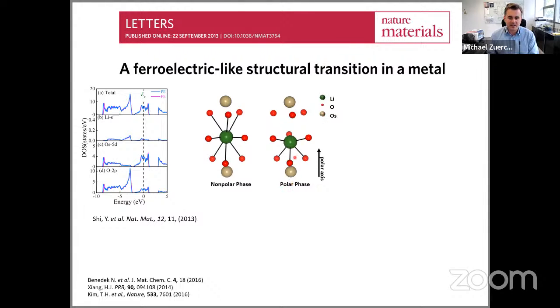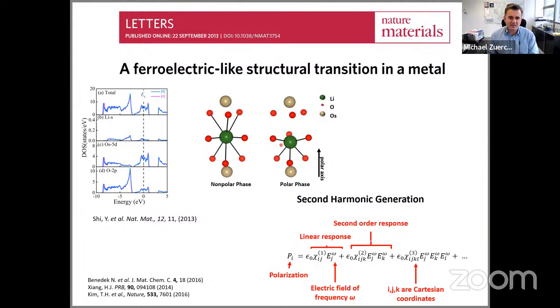So we took the approach of asking, can we do second harmonic spectroscopy resonant with lithium to learn something about the dielectric environment, with the idea, of course, that in the polar phase the symmetry is broken, so we expect second harmonic emission. The other thing, as I said before, is that this chi2 term, this nonlinear susceptibility, is a tensor with indices ijk, which you can think of like coordinates x, y, z. So this means there is some directional dependence in this tensor, with the tensor elements giving us different directions in the crystal. So if you measure this chi2 tensor specific to lithium, you get information about the dielectric environment as seen by the lithium atoms within the system. Okay, so this was the motivation for our measurements on this system.